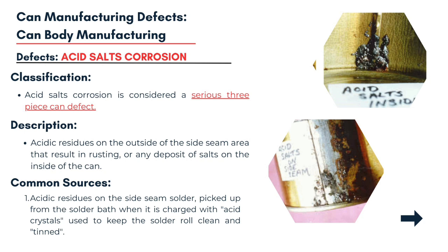If this bath is charged with acid crystals, a practice intended to keep the solder roll clean and metal tinned for better soldering, residual acidic compounds can be left on the can. So this serious defect directly threatens the can's hermetic seal, potentially leading to leakage, product spoilage, and even food safety concerns. This stringent control over the soldering process, including thorough rinsing and neutralization of any acidic residues, is paramount in preventing acid salts corrosion and ensuring the quality and safety of the 3-piece can.